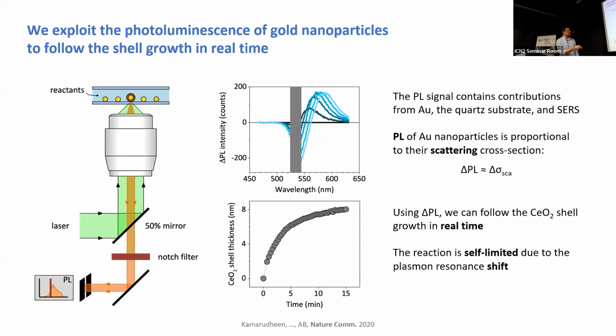So that's what we plot. We plot the ceria shell thickness as a function of time, and we saw that it was actually pretty fast at the beginning and then slowing down towards the end of the 15 minutes irradiation period. And we think that the reason for it is because the nanoparticle is heating up under the 532 nanometer irradiation, but as you grow a shell around it, the plasmon resonance is redshifting, but the laser irradiation is staying there, and so it's cooling down. It doesn't heat up anymore. So it's kind of a self-limited process.